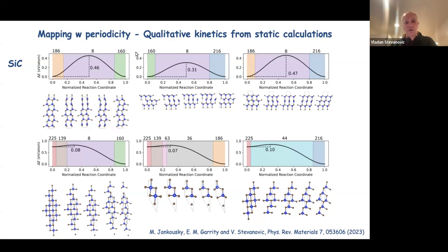Space group 186 is wurtzite, 160 is the rhombohedral, and space group 225, which is the rock salt. And these are the Bain mechanisms that our algorithm finds for the transformation from wurtzite to rhombohedral, rhombohedral to zinc blende, wurtzite to zinc blende, and rock salt to the other 3. So 4 polymorphs, sorry, rock salt is included.